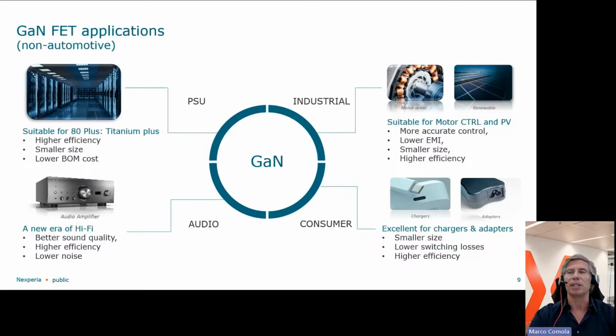So this is surely an added value of using gallium nitride. For the audio, for the hi-fi, and it's something that is already well known from the market, you have better sound quality using the gallium nitride. And you have higher efficiency in your application, so you can increase the power with the higher efficiency. And you have lower noise, so lower THD and lower oscillation and so on, lower EMI. So it's really a new era of hi-fi using the gallium nitride. And for consumer, we already told you, it's excellent for chargers and adapters, since you can decrease the size of your application, you have lower switching losses, you have higher efficiency, and at the end, you can also think to put the charger adapter inside your application because it's very small.